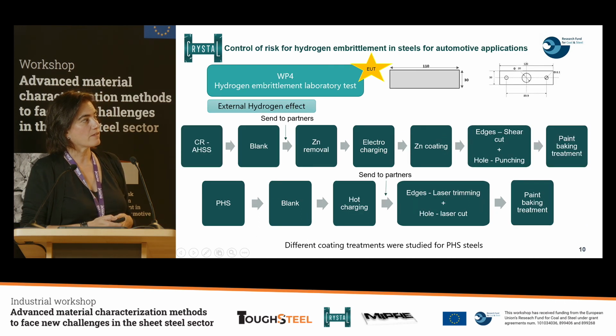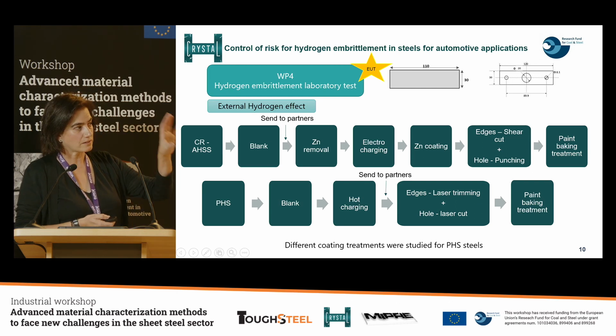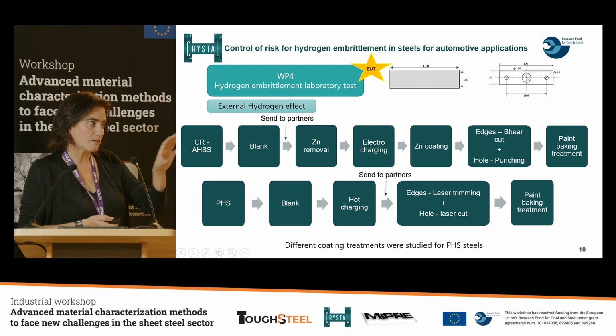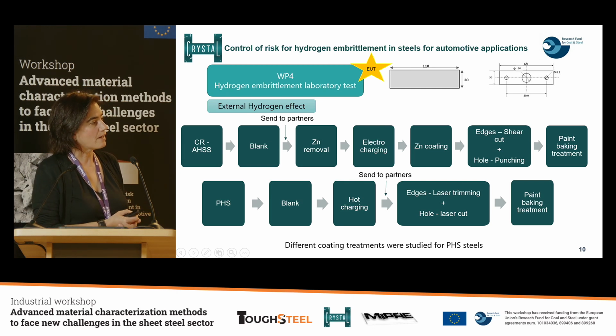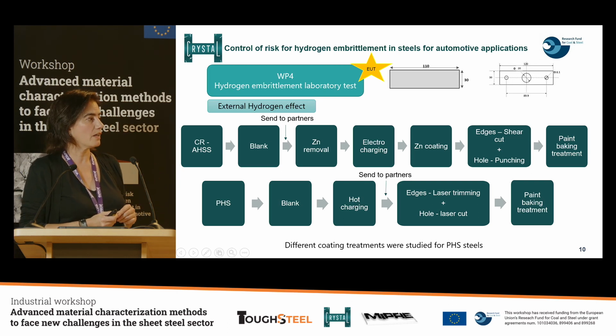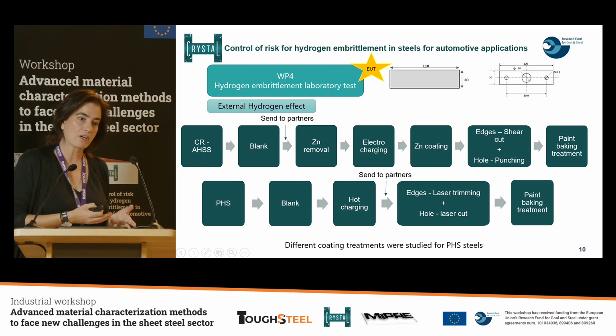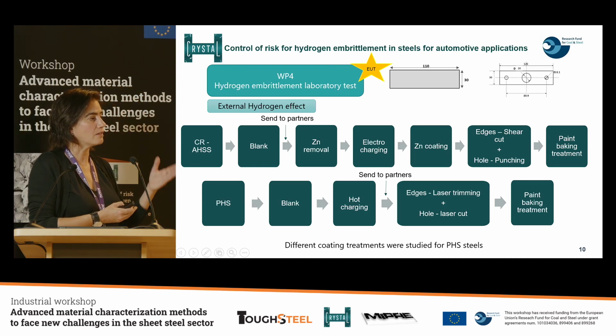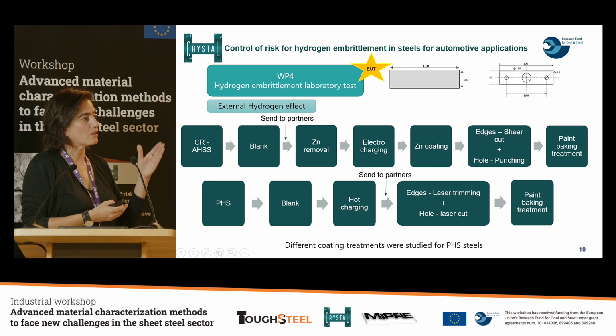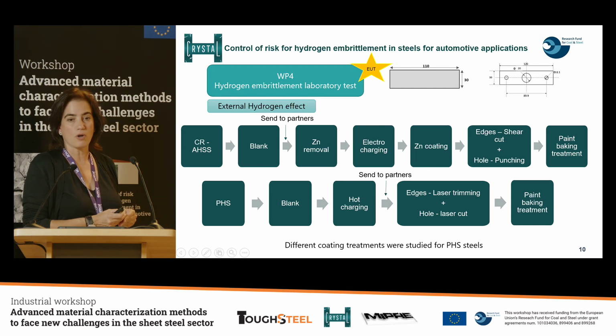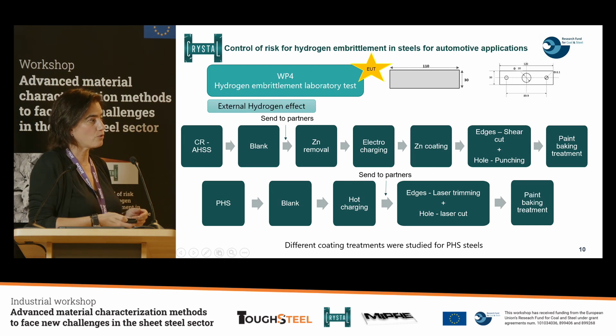In the case of external hydrogen, the samples were the same and the sample preparations were also the same, but we added a last step, a paint baking treatment, to be closer to reality. Also, we have to say that in the case of the PHS steel, we realized that it was very difficult to introduce hydrogen into the materials, so we decided to study the effect of hydrogen with different coating treatments, in the case of CR-AHSS and PHS steel.